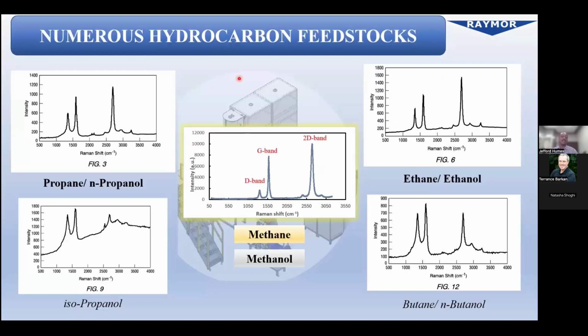What is great, though, about the technique that's used to produce this material is that we can produce it from numerous types of hydrocarbon feedstocks. We can use propane, ethane, or butane. But we've found that the highest quality material with the highest crystallinity, as can be seen from this Raman signature and spectrum here, is using methane or methanol to produce our Purewave graphene, with methane being the preferred feedstock for our material.